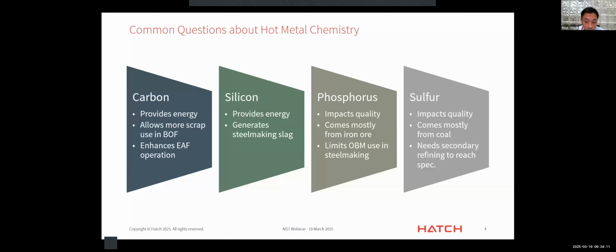Both carbon and silicon provide a lot of energy, and carbon especially is a primary energy source for BOF steelmaking, allows higher scrap use, does a lot of the refining in the BOF, and of course has a lot of benefits when used in the EAF as well, whether in energy benefits, as well as allowing effects like slag foaming to improve the quality and the efficiency of steelmaking.